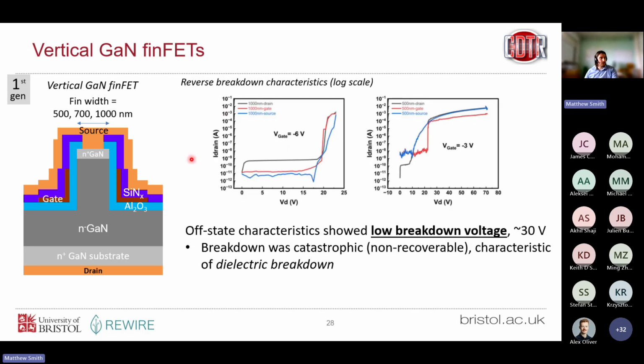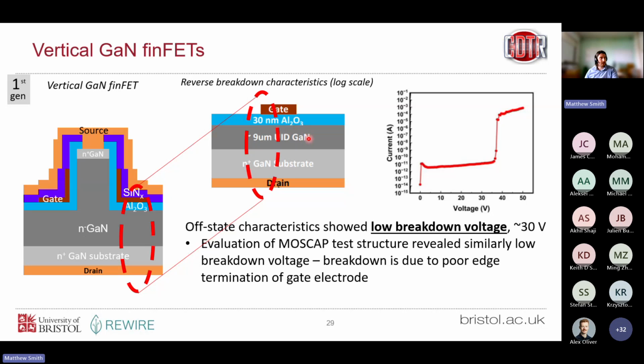So the bad news for this first generation was that they're very low breakdown voltage, so breaking down at somewhere like 30 volts. So for a power device, that's not good. We want to be up in the hundreds of volts or the thousands of volts, something like that. So we saw this catastrophic breakdown, non-recoverable dielectric breakdown, and what we think here is that it was breaking down in this essentially capacitor at the base of the fin there. So we looked at these MOSCAP test structures. So alongside the devices, we fabricate test structures on the chip, and we find that actually they have a fairly similar breakdown voltage and seems to be a similar mechanism as well. So it's a bit of a clue that that's what's going on there.